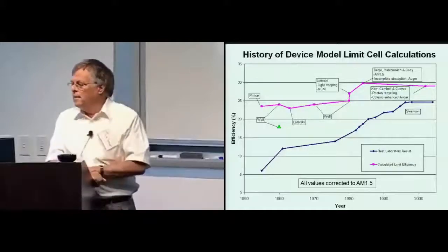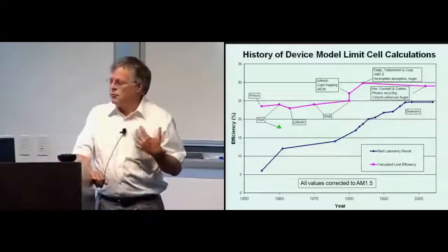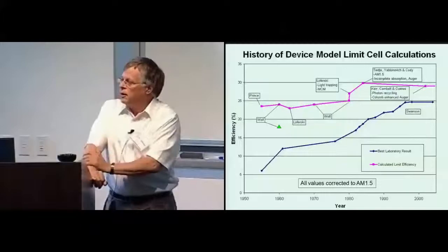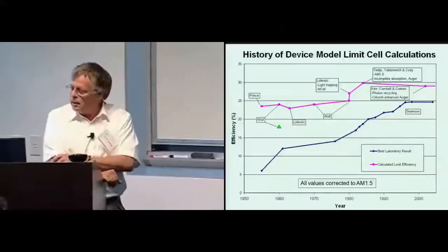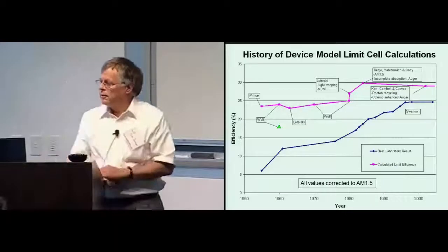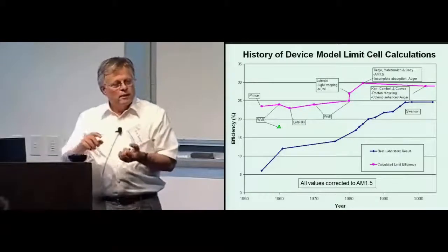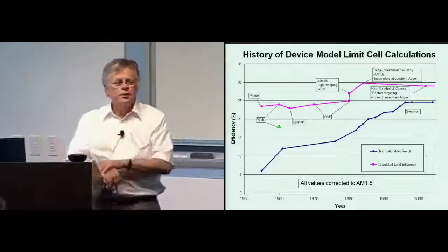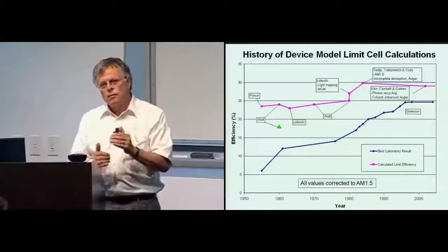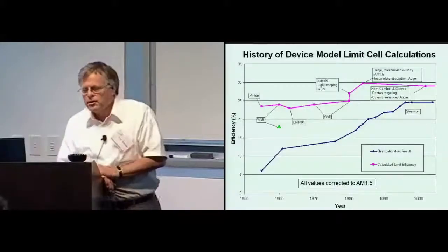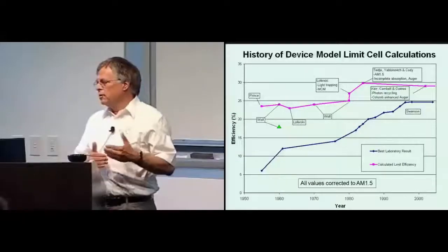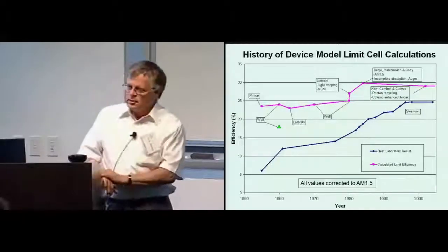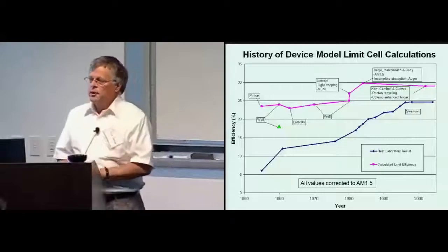And so people started working on how to best include radiative recombination. And Eli and his team came up with a model where they combined that with the exact absorption edge of silicon to get a much more realistic understanding of what the generation current would be, more accurate models of light trapping within the cell, and got an efficiency somewhere around 30%.